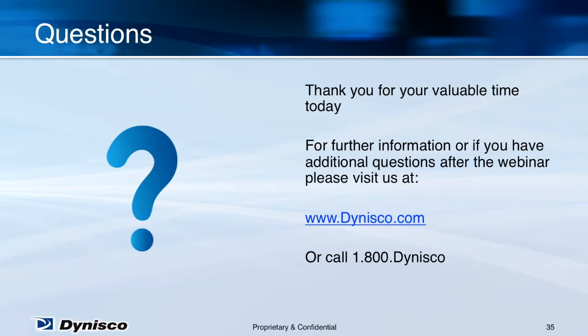Thank you. How many tests should I do on my melt flow indexer to obtain an accurate correlation factor for temperature variations? In the presentation, we fit the data to a line, so in theory, only 2 points are required. We would recommend an average melt flow index be determined over multiple tests at at least 2 different temperatures. I would recommend doing more than 2, though, so you can check the accuracy of the fit.